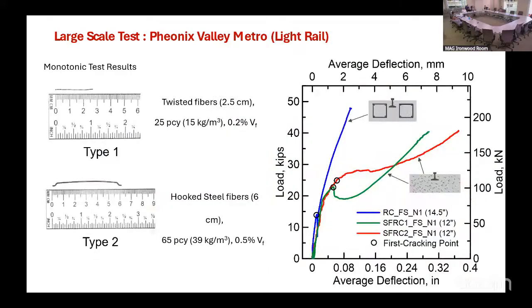Next slide, please. So what we did is that the blue line shows you the standard concrete reinforcement. It cracks at about 13,000 pounds. That's when the initial cracking of the concrete occurs, with that blue circle. But the fibers that we use crack at a much higher load, about 20,000, because the fibers act to suppress the cracks. And I'll show you pictures of how it happens. And then after that, you have a residual capacity that the fibers are providing.